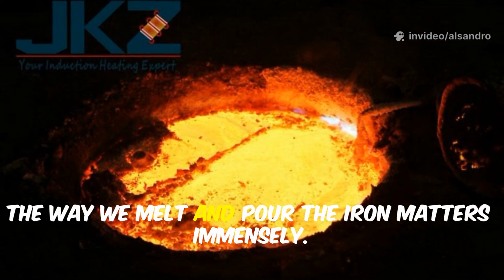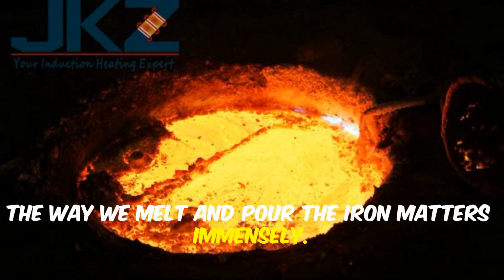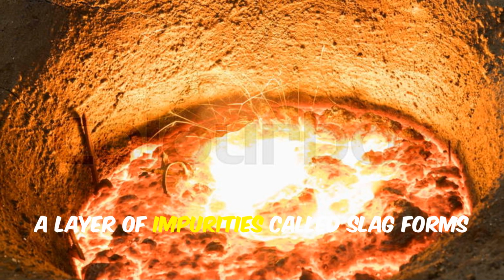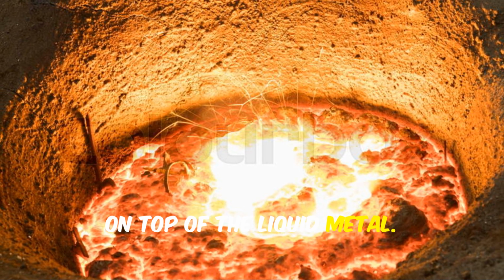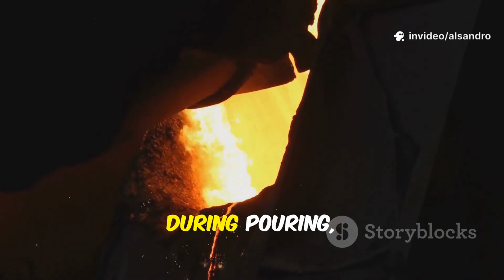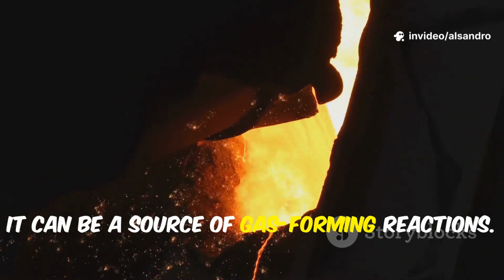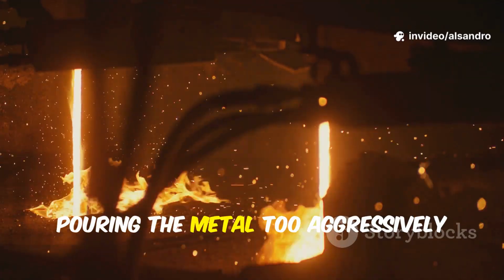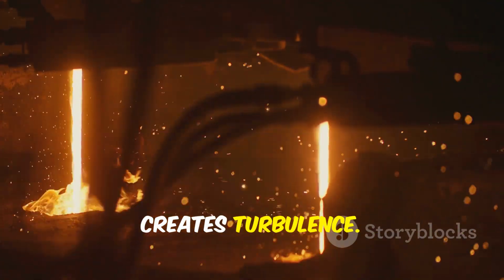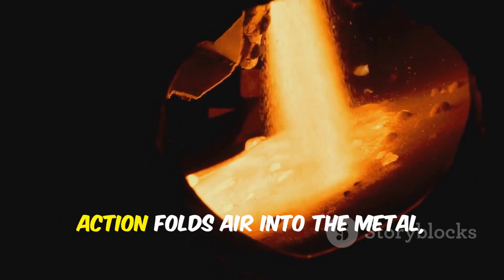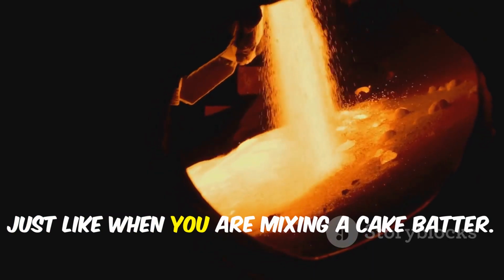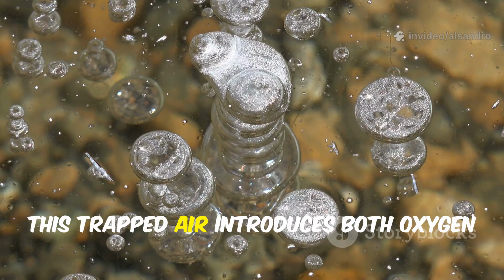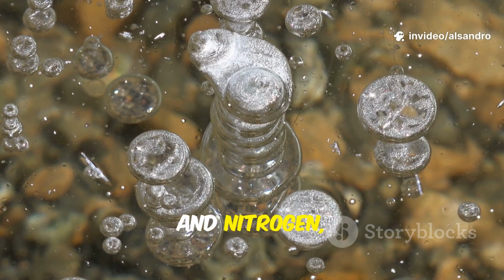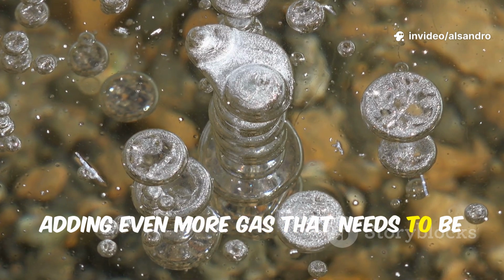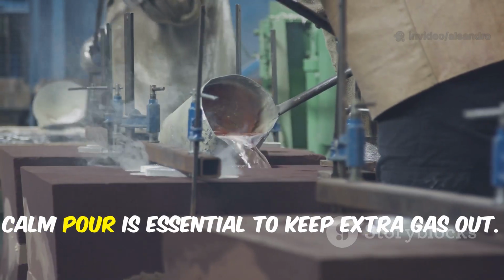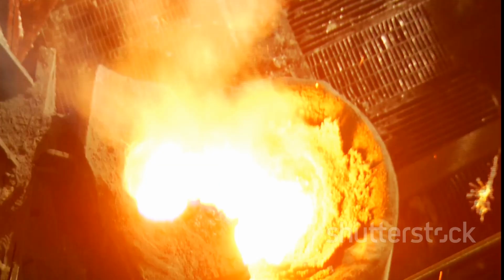Finally, the way we melt and pour the iron matters immensely. During melting, a layer of impurities called slag forms on top of the liquid metal. If this slag gets mixed into the iron during pouring, it can be a source of gas-forming reactions. Furthermore, pouring the metal too aggressively creates turbulence. This violent splashing and tumbling action folds air into the metal. Just like when you are mixing a cake batter, this trapped air introduces both oxygen and nitrogen, adding even more gas that needs to be dealt with. A smooth, calm pour is essential to keep extra gas out.